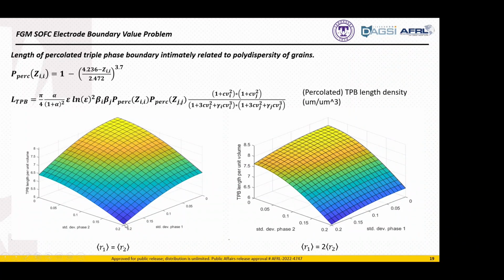Suffice it to say, we maximize our triple phase boundary, or the length along which these electrochemical reactions are taking place, if we minimize the standard deviation of both particle phases, so for an anode, the nickel and the YSZ. We want to make that as monodisperse as possible, and we want to try and closely align the average particle sizes as well. But as we see from the graph on the right, the triple phase boundary is less sensitive to changes in the smaller particle size. So if the average particle diameter of phase 1 is twice that of phase 2, then I can increase the standard deviation of my smaller particle phase and not negatively affect the triple phase boundary quite as much.